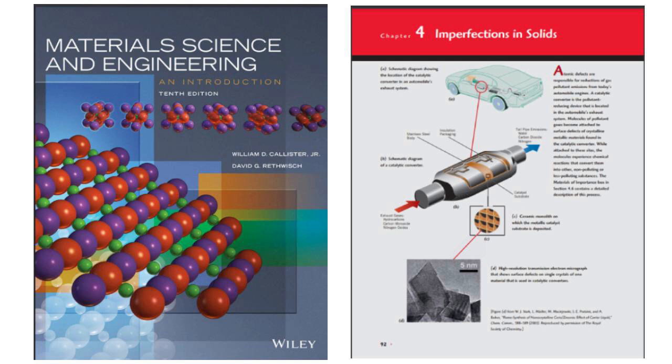That's incredible. But how do material scientists even know which atoms will mix well together? Is it just trial and error, or is there some kind of science to it? There's definitely a science to it. There's a set of guidelines called the Hume-Rothery rules, and these help predict whether two elements will form a solid solution, which is a mixture where the atoms are evenly distributed. These rules consider factors like atomic size, crystal structure, electronegativity, and the number of valence electrons that each atom has.